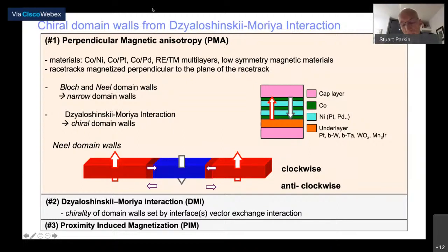This was found many decades ago in a number of different systems. But this is very interesting. Depending on whether we use platinum or tungsten or iridium, we can get a different chirality of the domain walls, but all the domain walls in the racetrack formed in this cobalt-nickel multilayer will have the same chirality. If we use an underlayer, let's say of platinum, it will be clockwise. If it's a different material, it can be anti-clockwise. Later on, you'll see why this is very important.